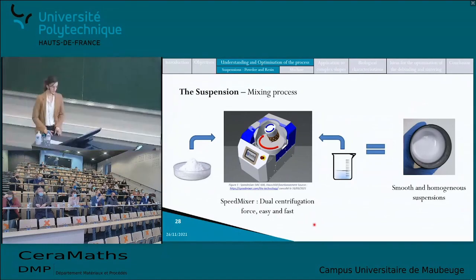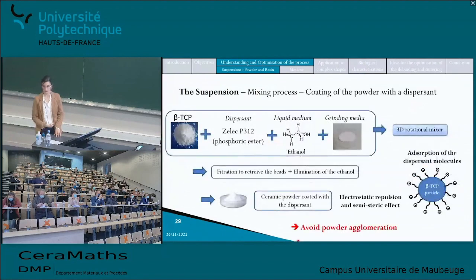But the powder also has to be coated with a dispersant in order to be mixed with the resin, because the powder mixed with the resin on its own agglomerates and creates a non-homogeneous suspension with a shear thickening behavior. So I chose the Zelec P312, which is a phosphoric ester, as a dispersant, and I mixed it with my powder in ethanol with a grinding media. All of that went through a 3D rotational mixer. Then the beads were filtrated and the ethanol eliminated, leading to the obtention of the ceramic powder coated with a dispersant. How does the dispersant work?